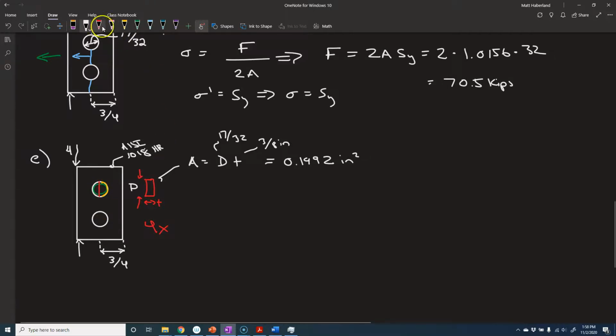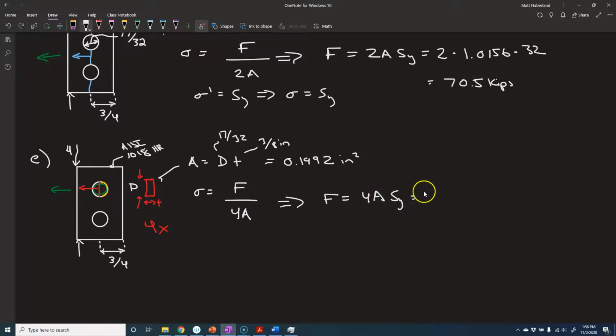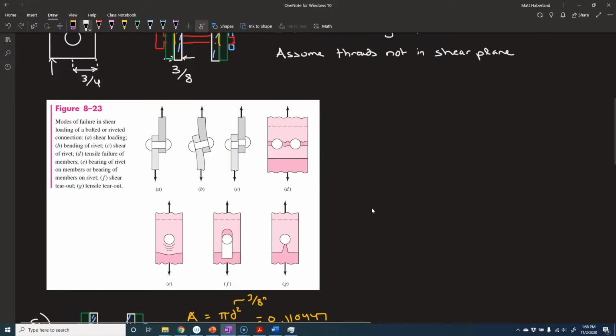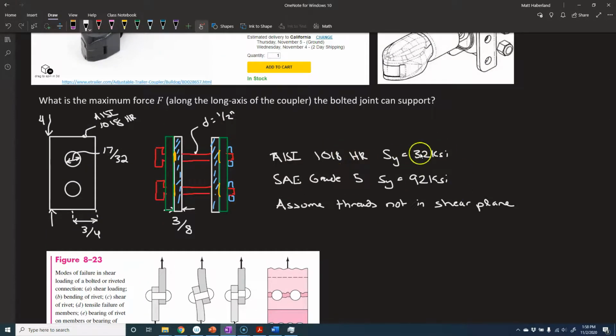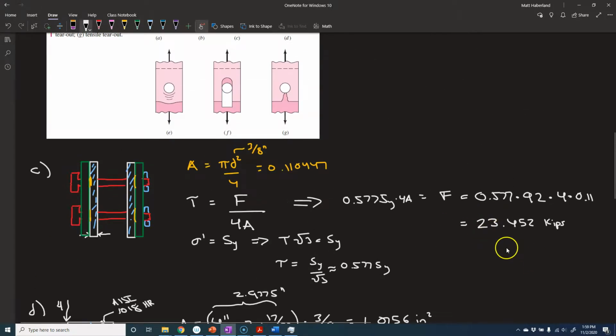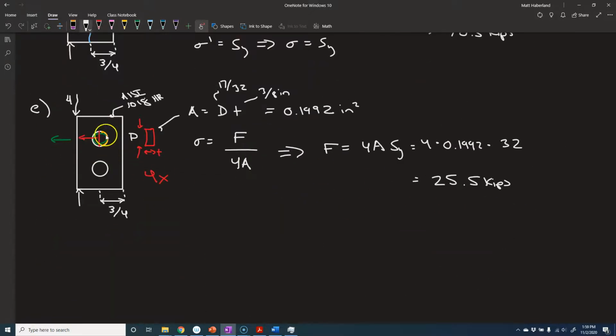Well, the normal to this plane is in this direction, the same direction as the applied load. So we've got a normal stress, and the normal stress value is the force divided by 4 holes times that area. But we know that we yield when F is equal to 4A times the yield strength. We've got 4 times 0.1992 times the yield strength. Which yield strength are we talking about? Well, we're talking about whichever is smaller between the bolt and the part. In our case, the part is what's going to yield first, 32 KSI. That's 25.5 kips. So it looks like the first thing to fail is still going to be the bolts themselves. Now, this is just an approximation. You're probably going to get some local yielding, but it's not going to be some gross yielding.